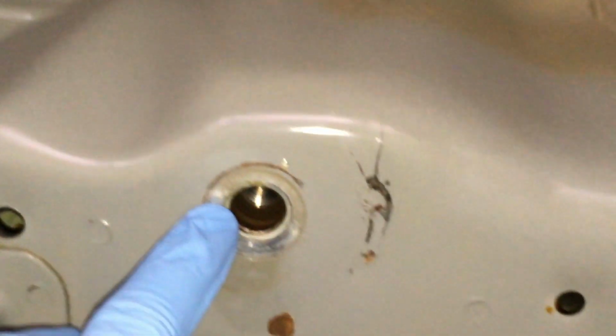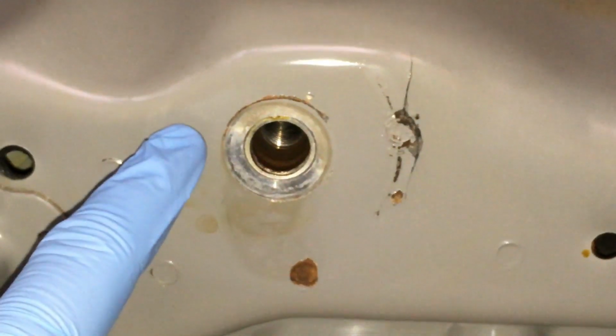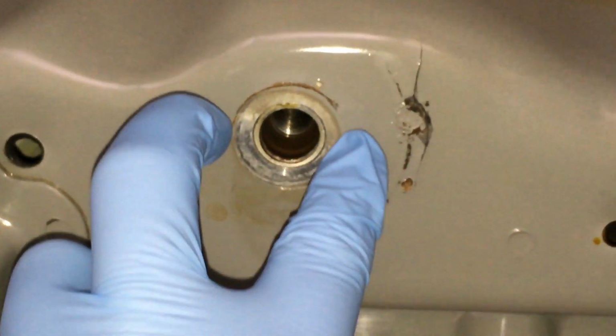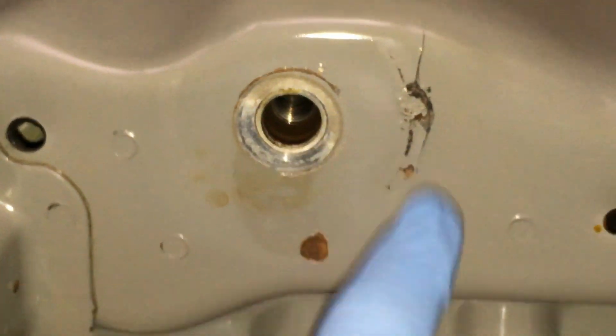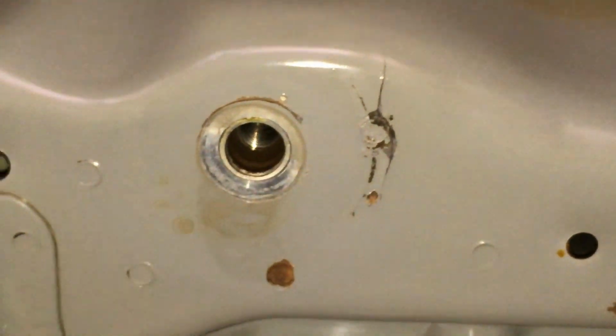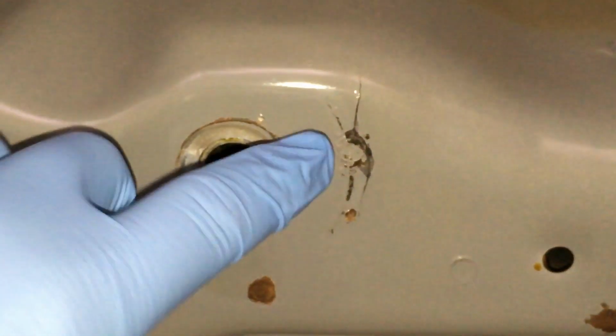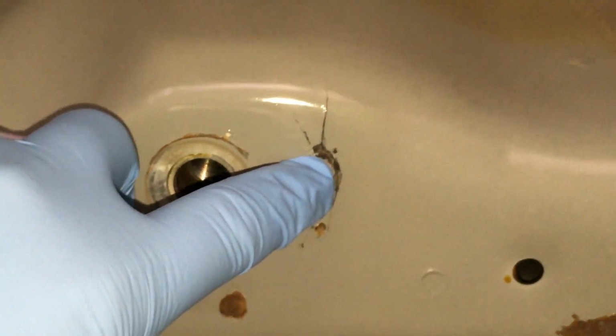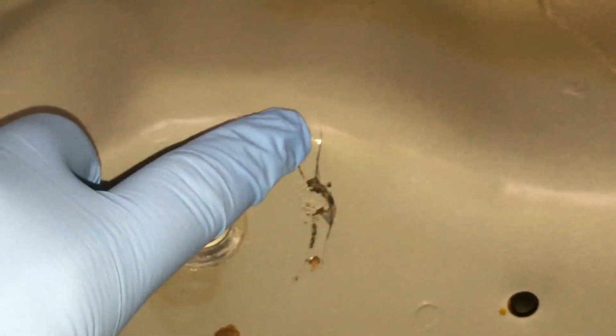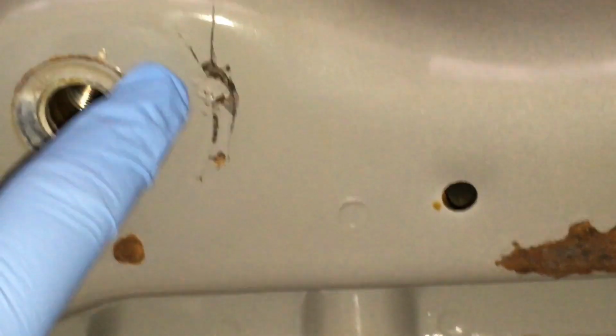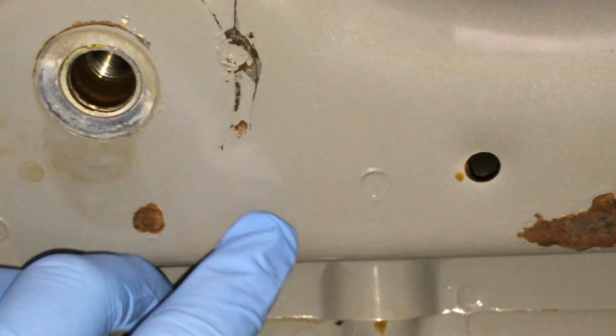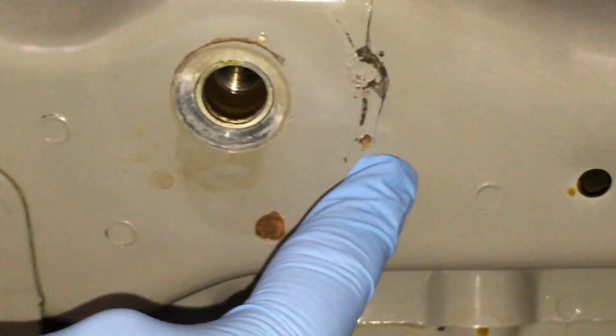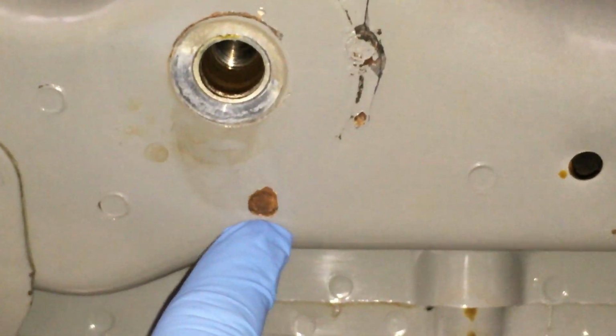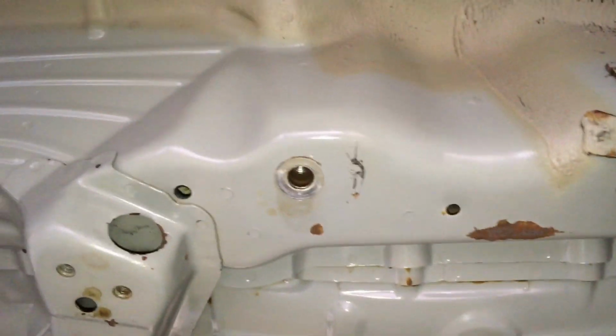And then the right front mount is definitely cracked. This one's quite easy to see. We've got a small hairline crack from here going around the mounting point to over here. We've got a spot weld which is broken where the bush has been impacting its lips, and now it's not only broken the spot weld, but it's caused a crack to go towards the back of the car and then up the vertical section very slightly, and then also come out of that spot weld and go forward, and at the moment it ends somewhere around there. So that spot weld's flexing, whereas these ones are all looking okay at the moment. So that's the four mounting points.